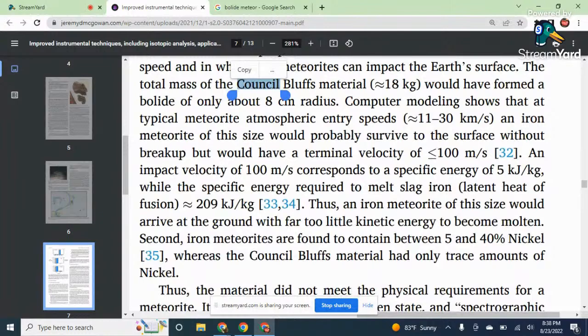less than 100 meters per second. An impact velocity of 100 meters per second corresponds to a specific energy of 5 kilojoules per kilogram, while the specific energy required to melt slag iron, latent heat of fusion, is approximately 209 kilojoules per kilogram. Thus, an iron meteorite of this size would have arrived at the ground with far too little kinetic energy to become molten.